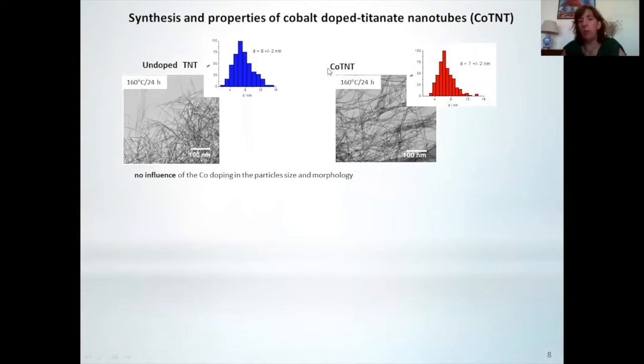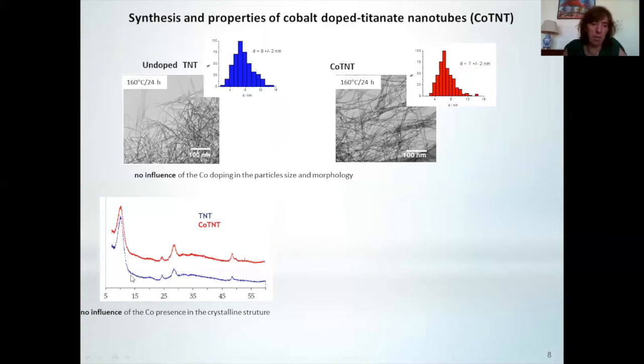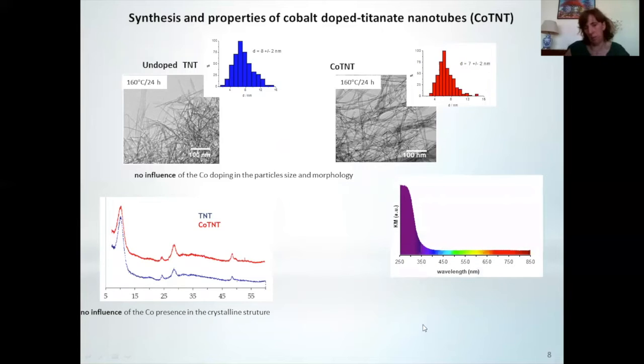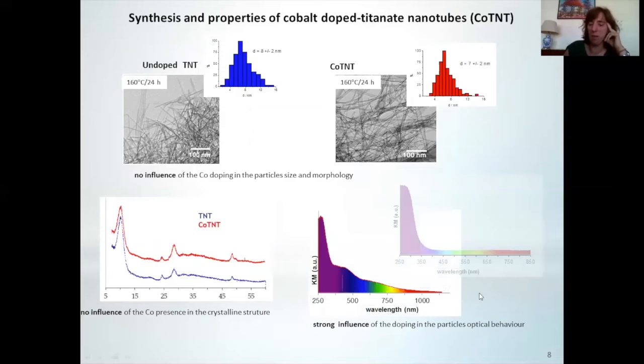We have tested this, for instance, with cobalt. We have prepared a doped sample, titanate nanotubes. In this case, we have no changes in the morphology. I must say that this is not true for all the conditions that we can use, but in this case, we have no problems with morphology. If we look at the XRD, for instance, this is the peak that I told you is very important and tells us about the interlayer distance. So we look here, we have no shifts. So this is telling us that all the cobalt is replacing the Ti4+ in the structure. But if we look at the optical spectrum, we can see that after doping, we have not only a shift in the band edge absorption here, but we also have the contribution of the d-d transition of the metal, the cobalt.